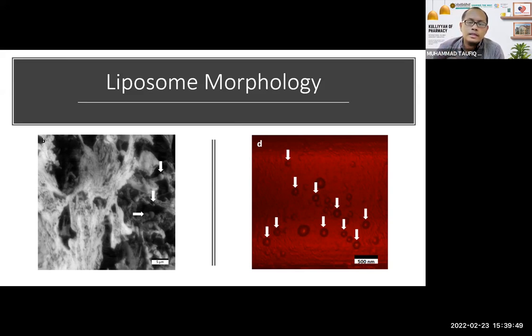So liposome really doesn't like dryness. If you put it on the flat surface and you dry it, it will become something like a jellyfish on the beach. Initially, it becomes spherical on the surface because of the surface tension. But when you dry it and put it on the surface, it just lies flat. Now, when it lies flat and you measure the size of it, there is some contention on how you want to say whether the size is correct or not. Because imagine a jellyfish in the ocean, the diameter of it compared to a jellyfish on the beach, they have different diameters because you lie it flat.